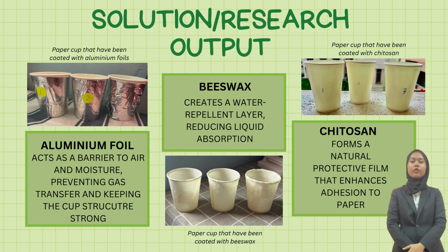For the solution or research output, we use 3 main materials for our coating. First, aluminium foil. It acts as a strong barrier against air and moisture, helping the cup stay firm and prevent leak. Next, beeswax. It forms a water-repellent layer that reduces liquid absorption. Lastly, chitosan. It creates a natural protective film that improves the bonding between the coating and the paper cup.